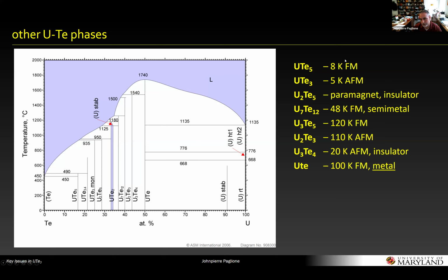And I just quickly went through the literature to point out the different ground states or magnetic states that are seen in these crystals. So ferromagnet, antiferromagnet, etc., metals, insulators. Uranium tellurium 1, for instance, can really fool you. It's a metal, and it has a 100 Kelvin ferromagnetic transition. So if someone shows you susceptibility of a high TC crystal grown by salt flux, I would urge you to ask them, what does the susceptibility look like at 10 kilo-oersted, not measured in 1 Tesla? And if you see signatures of this, you have to worry what kind of contaminant phases might be in these crystals. So just a word of warning about comparing things.